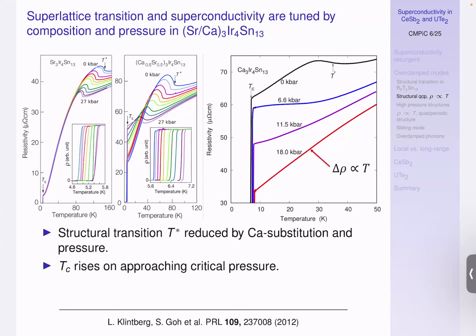And the striking thing is, of course, it was motivated by the idea of maybe something interesting happens to the superconducting transition, and it is interesting, but it's not super interesting. TC goes up a little bit. But what was really surprising was that the resistivity becomes linear in temperature down to TC.